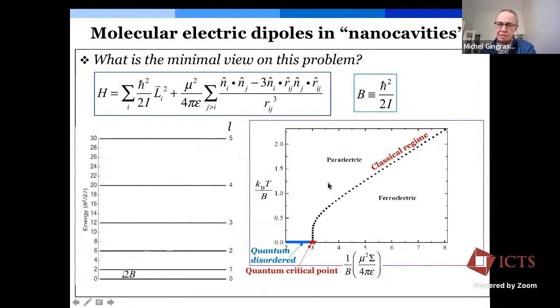And so what I will present to you today is, I believe, the first survey of that kind of phenomenology within a very limited theoretical perspective. And so this is the phase diagram as a cartoon. k_B T here is the thermal energy, T is the temperature, B is the rotational constant for the linear rotor, h bar squared over 2I. And the horizontal axis is the ratio of the dipole-dipole interaction energy scale divided again by the rotational constant. So the two axes here are dimensionless, and sigma here is a placeholder for the dipolar lattice sum for the system. The long-range dipole-dipole interaction here has to be handled without truncating it, and so it has to be computed using the Ewald summation method, for example.